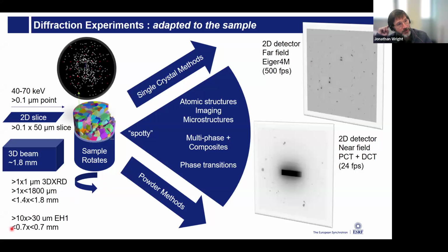So we have ways to change the beam size. You can have a very small X-ray beam. You can have a slice of X-ray beam to take slices through the sample, or you can have a large X-ray beam to illuminate a volume, and you can also use that for tomographic imaging. You can then collect the diffraction with a near-field detector, so the detector very close behind the sample, and you see directly the shapes of the grains, or with a far-field detector that's very far back, and you see directly the scattering angles.